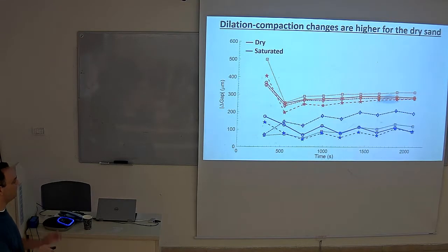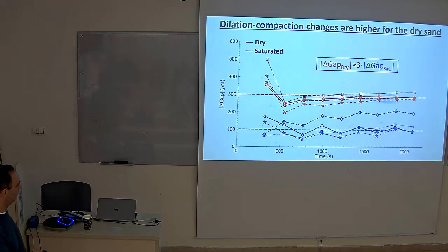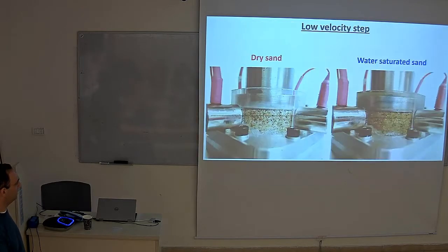Let's take a look just at the delta gap, the absolute value of the delta gap versus the time of the experiments. So each point is a jump between low and high velocity. And what we see is that the dry is always higher than the saturated experiments, and it's about 3 times larger, the delta gap. So the question is why? Now let's see if we can get something from the experiments themselves, looking at the video.